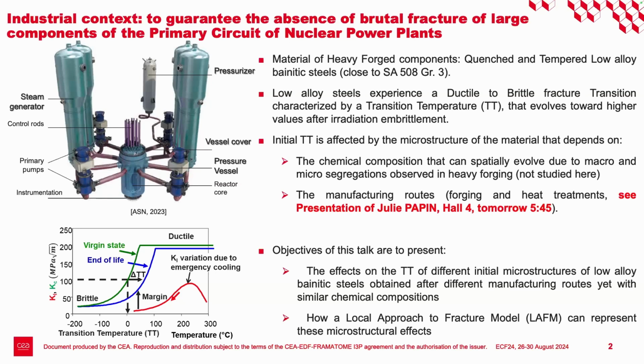But in this talk, we are going to focus more on what can affect the initial transition temperature. Basically, it's due to modifications of the microstructure of the material. This modification can come from the chemical composition. Because of the size of the components, you have differences in the chemical composition depending on where you are in the component. And you also have an effect of differences in the quenching rates and tempering parameters. Again, depending on whether you are inside the thickness of the thick component or in the skin, you don't have the same value of quenching speed, for instance.